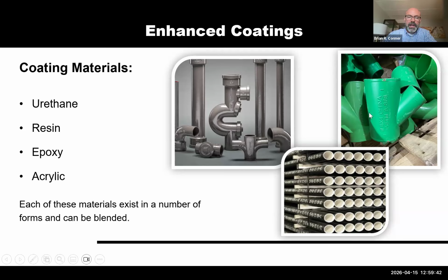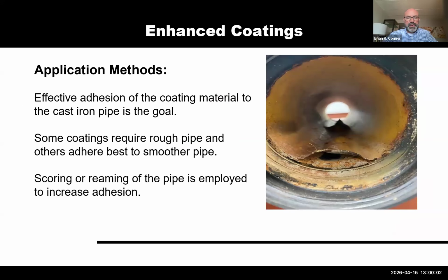But the offshore folks from China also adhere their coating in a different way. We are the only ones who use the E-coat, which makes sure that the coating is electrostatically adhered to the substrate so that there can be no delamination, and others have not used that technology. So because of that, there is ability for some of the others in the market to have delamination because the chemicals, or the aggressive effluents, can get in between the iron and the coating itself, and cause corrosion.